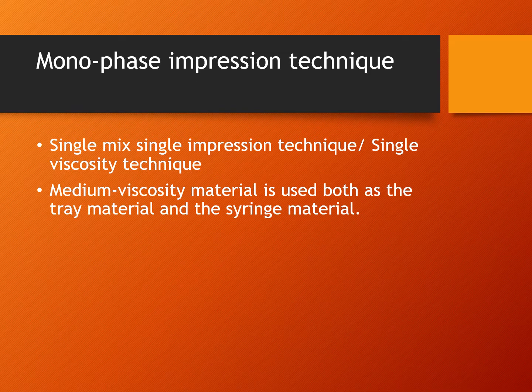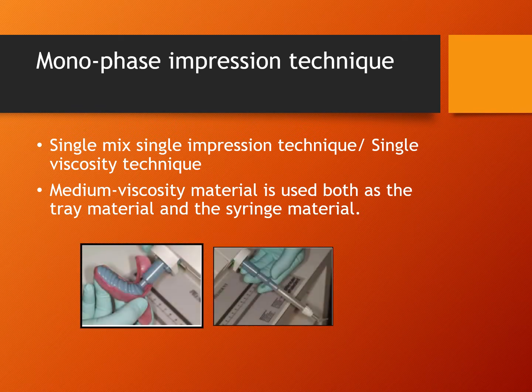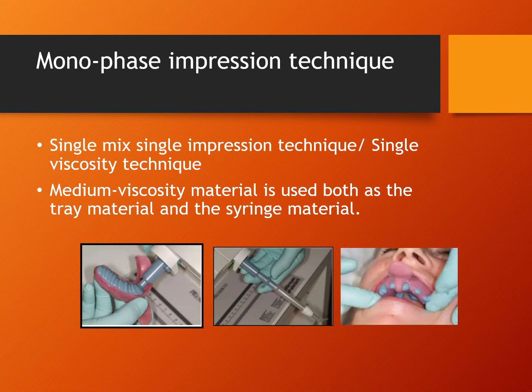The monophase impression technique is also called the single mix, single impression technique or single viscosity technique. The procedure is the same as that of the dual phase impression technique, except that medium viscosity material is used both as the tray material and the syringe material. A medium viscosity, that is regular body impression material, is placed in a custom tray with a 3 mm spacer, and the surface reproduction may not be as good as that of a light body material in this technique. Also, the medium viscosity material will show a greater amount of polymerization shrinkage compared to the heavy body because of less filler content.